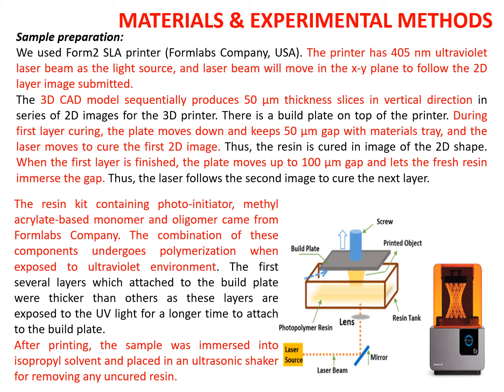When the first layer is finished, the plate moves up a 100 micron gap and lets the fresh resin immerse the gap. The resin kit containing photoinitiator, methyl acrylate-based monomer, and oligomer came from Formlabs company. The combination of these components undergoes polymerization when exposed to UV environment.